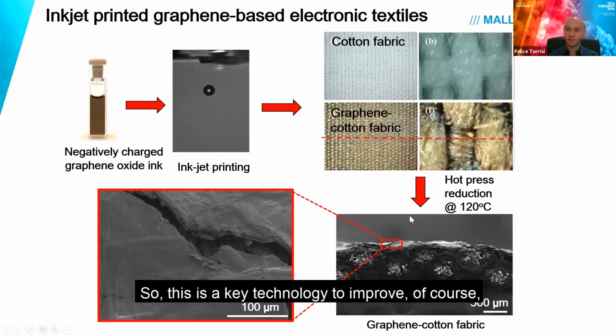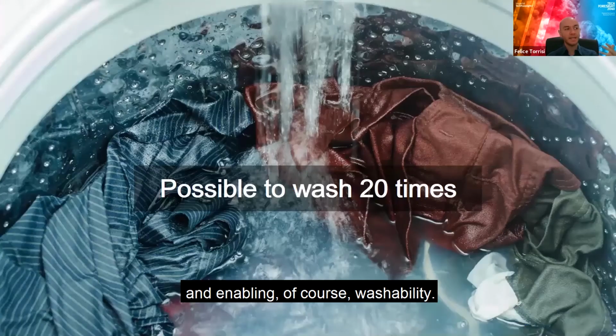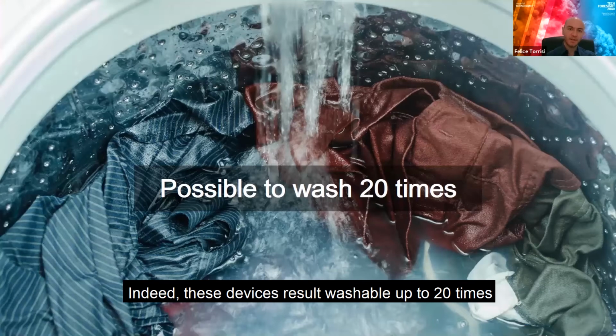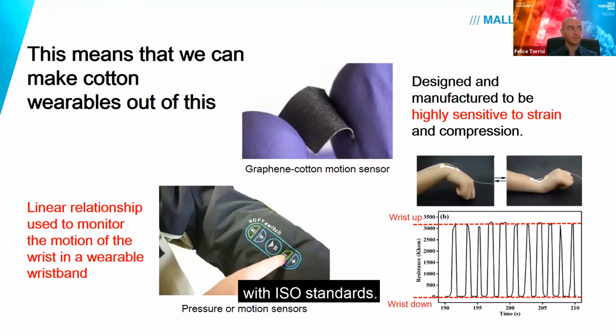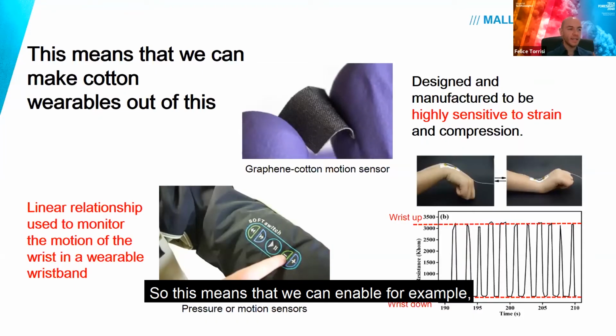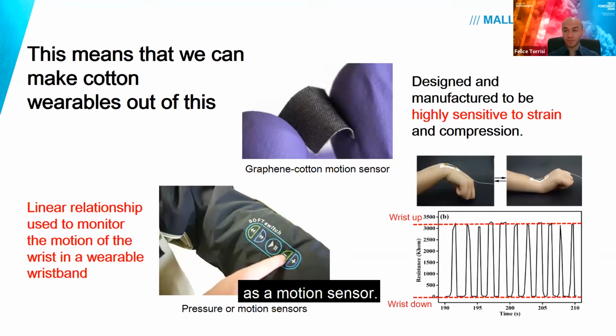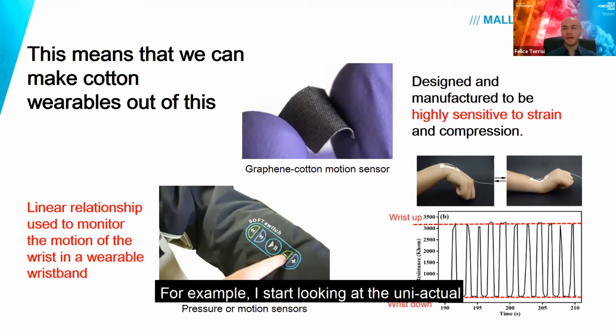So this is a key technology to improve, of course, the adhesion to the substrate and enabling, of course, washability. Indeed, these devices are washable up to 20 times with standard washing procedures with ISO standards. So this means that we can enable, for example, truly textile, actually in this case, cotton textile wearable devices. Initially, I started using this graphene cotton fabric as a motion sensor. For example, I looked at the uniaxial and biaxial monitoring of the wrist position using, for example, strain, change, and compression. And this allows a constant and very robust way of monitoring the position of our wrist as a function of a change in resistance.